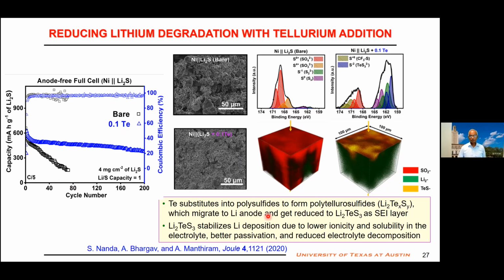So what does tellurium really do? When you add tellurium, it substitutes into the polysulfide, Li2S6, for example. In that, part of the sulfur is replaced by tellurium because they are in the same group. Once it does that, it forms something called Li2TeS3. So this forms on the lithium metal anode as a robust in situ formed SEI on the lithium metal anode, and that helps to keep better cyclability, or better stability, or better plating and stripping efficiency with the lithium metal. That is what is happening. So that improves the cycle life as well as the lithium deposition morphology and other things.